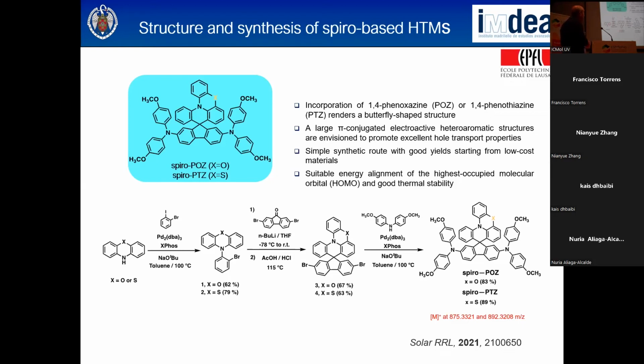So you can see, from commercially available phenoxazine or phenothiazine, in 3 steps with relatively good yields without optimizing, this is a reaction with 2-bromo iodobenzene, and you get this compound. Then replacement of the bromine by lithium in the presence of butyl lithium in THF at low temperature gives you the lithium, and then the nucleophilic attack on the carbonyl group, and eventually you get a carbinol. Sorry, this is only for organic chemists, but I will finish immediately.